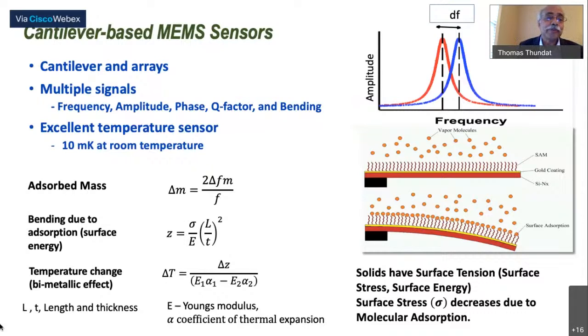So adsorbed mass, we can detect just by measuring the delta F, which is the shift in frequency with respect to the original frequency and the mass of the device. Mass of the device is mostly nanograms. You can even tune it to even smaller devices.